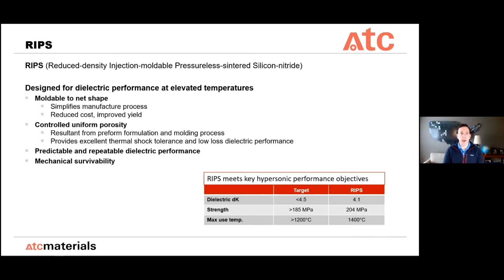So RIPS, I've said RIPS a few times. What is RIPS? It's a DoD approved belabored acronym of reduced density injection moldable pressureless sintered silicon nitride. So that describes the material and how it's made. It's designed specifically for dielectric at high temperatures. And the way we get there is it's molded to net shape. So it's a simpler manufacture process than a traditional sintered silicon nitride. And for final products, it's better yield and reduced cost compared to billets that need to be machined to shape. Controlled uniform porosity, that's how we get there. That's what allows the dielectric properties as well as the thermal shock tolerance, and then mechanical survivability.